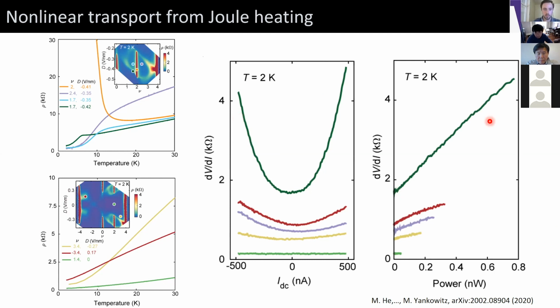And this is somewhat of a unique system. The base temperature resistivity can be quite high, on the order of kiloohms, so the heating can be quite substantial. And also the temperature dependence can be very large at low temperature. So for example, this green curve, as we heat, the resistivity grows quickly. So there's somewhat of a positive feedback mechanism in the sense that once we start heating it, the resistivity gets larger and then it's easier to heat it. And so the nonlinearity grows and grows. So we think that despite superficial similarity to superconductivity, we're pretty sure that this is actually a heating effect. And we also never see that this device resistivity actually saturates to zero resistance.